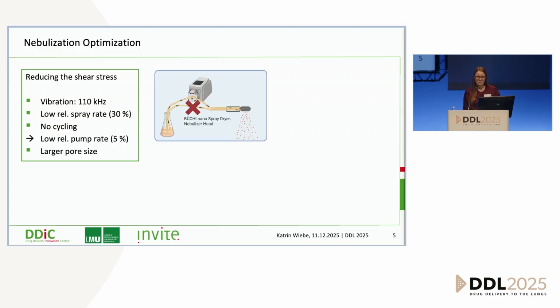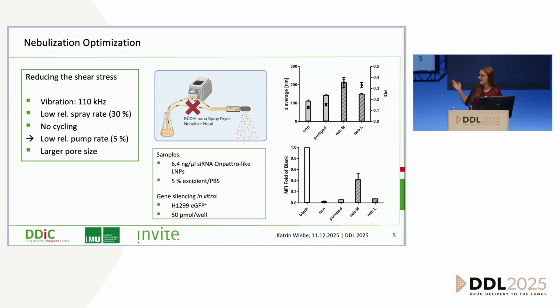And also, we don't want to cycle our LNPs. So this device is made in a way that you will pump the feed inside the head, and then only part of it will be nebulized. And then the rest will be pumped back into the feed again and pumped inside the head again. And this cycling really poses too much shear stress on LNPs. And we see that they aggregate a lot and they don't work anymore. So I really had to tweak the pump rate with the nebulizing rate to really have almost everything nebulized at the first attempt. And as you can see, above you can again see the size, down you can see how they performed in vitro. The pumping, in the end, really wasn't an issue anymore.